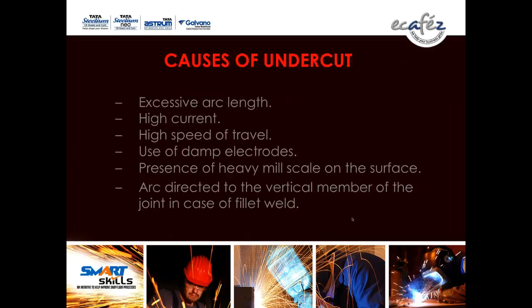Causes of undercut. These four: crack, lack of fusion, lack of penetration, undercut are called linear defects. Linear defects are dangerous for welding, not permitted in welding. So causes of undercut: excessive arc length, high current, high speed of travel, use of damp electrodes, presence of heavy mill scale on the surface, rusty surface, arc directed to the vertical member of the joint in case of fillet weld.